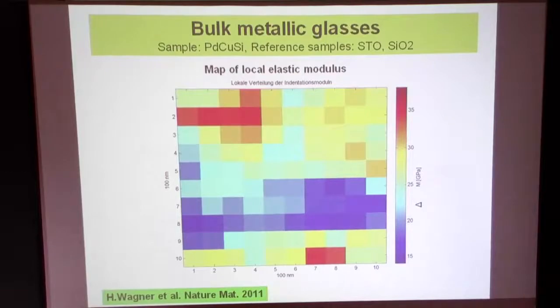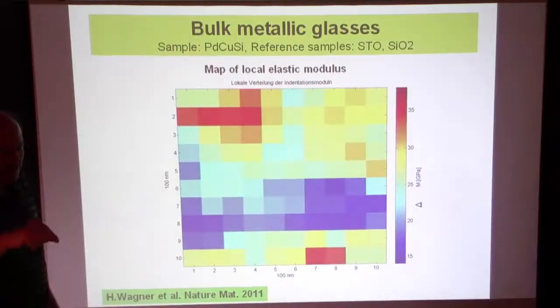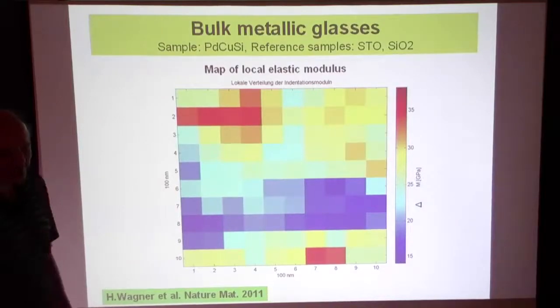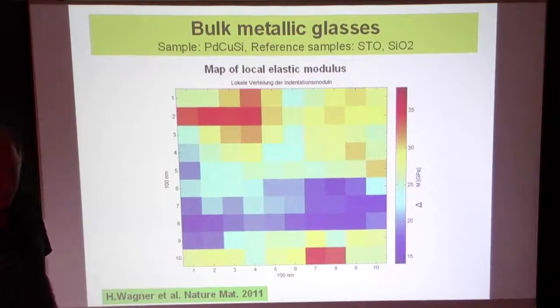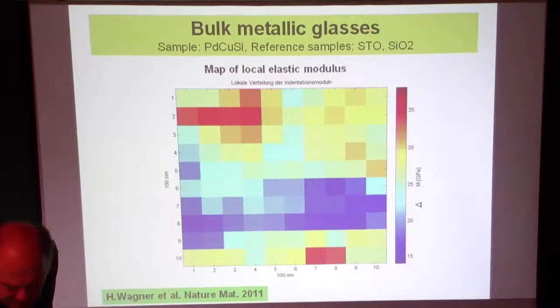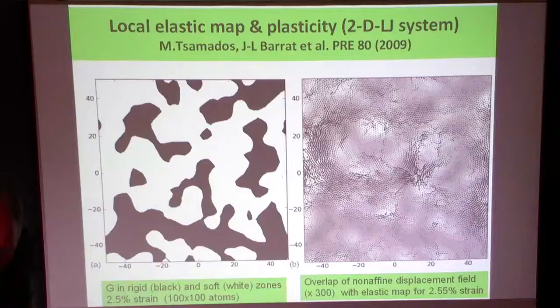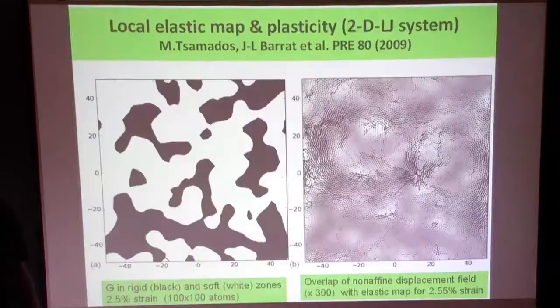What's the average? I showed to you the average is, well, the absolute value for the average we measure globally with ultrasound, okay? And then you see that's the deviation from that. But what is the average? The other ones were plus or minus 3%. 60 gigapascal. The model. Okay. So sorry, 60 GPa is what you're saying. Yeah, something like that. So you're saying plus or minus 10 on top of 60. I'll show it to you in a minute, okay?